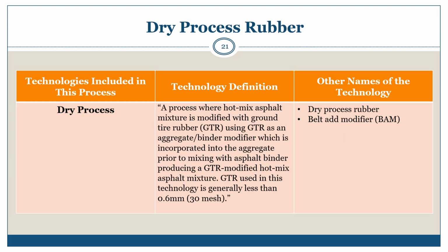Dry process rubber is defined as a process where hot mix asphalt mixture is modified with ground tire rubber using GTR as an aggregate/binder modifier, which is incorporated into the aggregate prior to mixing with asphalt binder, producing a GTR modified hot mix asphalt mixture. GTR used in this technology is generally less than 0.6 millimeters or 30 mesh. Other names for this technology include, with appropriate acronyms, dry process rubber and belt add modifier.